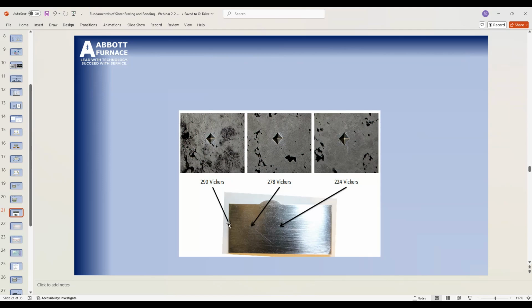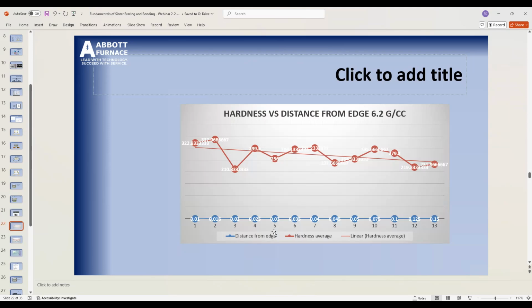And notice we've got a 290 Vickers on the surface. We come in slightly, it's 278. We come in even further, it's 224. The amount of carbon that we pushed in there keeps going down. So we really did stop it from flowing by carburizing the surface slightly. Okay, and here again is some more data on that. This is the distance. If we go from edge to center, you can see here the hardness values as we go through that.